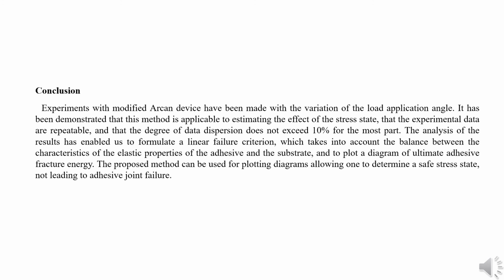Experiments with the modified Arcan device have been made with a variation of the load application angle. It has been demonstrated that this method is applicable to estimating the effect of the stress state, that the experimental data are repeatable, and that the degree of data dispersion does not exceed 10% for the most part. The analysis of the results has enabled us to formulate the linear failure criterion. The proposed method can be used for plotting diagrams allowing one to determine a safe stress state, not leading to adhesive joint failure.